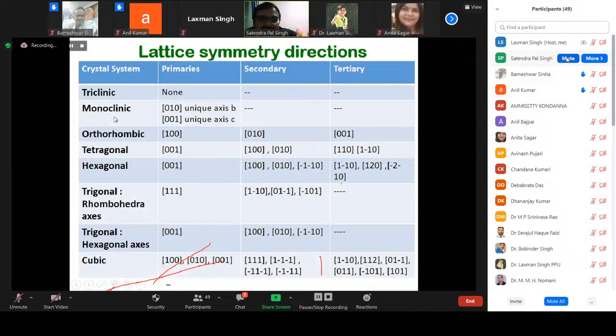Now, the other important thing is the lattice symmetry directions, in which directions all these symmetry operations are going to be done. So in the case of triclinic, we don't have any particular symmetry direction. But in the case of monoclinic, we have the symmetry direction along the b axis. This is called the unique b axis or c axis. As I told you earlier while describing the crystal systems, the monoclinic can have alpha equal to gamma equal to 90 degrees and beta not 90 degrees, or alpha equal to beta equal to 90 degrees and gamma not 90 degrees. That condition constitutes the monoclinic system with a unique b axis or unique c axis.